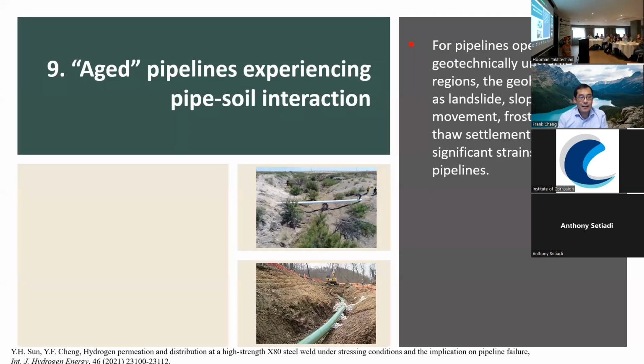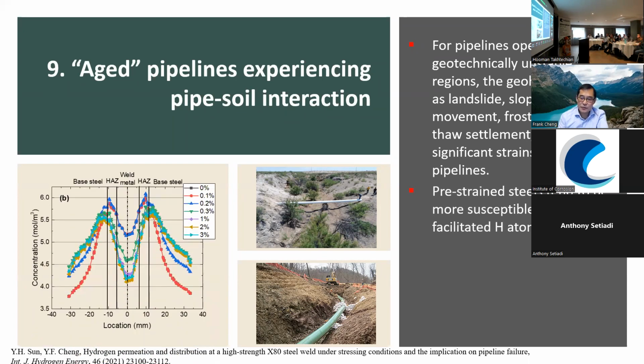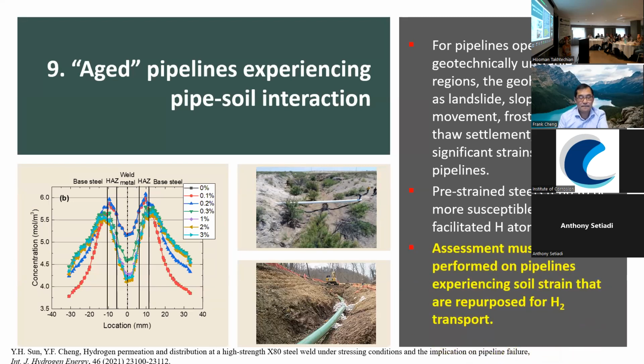So that's the aged pipeline's surface defects. At the same time, the aged pipeline usually experiences pipe-soil interaction, especially in geotechnically unstable regions such as mountain areas. The research results have found that if the soil induces a certain strain on the pipeline steel, the pre-strained steel is sensitive to local hydrogen trapping and consequently hydrogen-induced cracking. So that's why simulating the pipe-soil interaction to evaluate how soil strain influences hydrogen accumulation is a very important technical evaluation program.